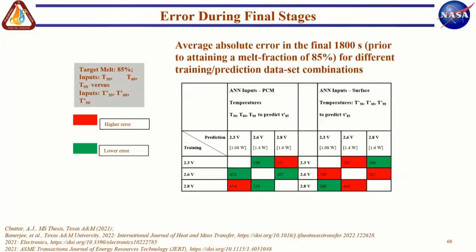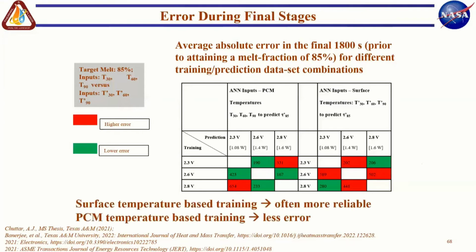On the other hand, the surface temperature data tends to do under prediction, which avoids catastrophic failure. So in other words, the surface temperature measurements are actually giving you less accuracy, but are more reliable. On the other hand, the ones that are based on the actual PCM temperatures are more accurate, but tend to be more unreliable because they tend to over-predict at times, and that can actually lead to catastrophic failure of your thermal power plant. So just to summarize, the surface temperature-based training is more reliable, and the PCM temperature-based training gives you less error.